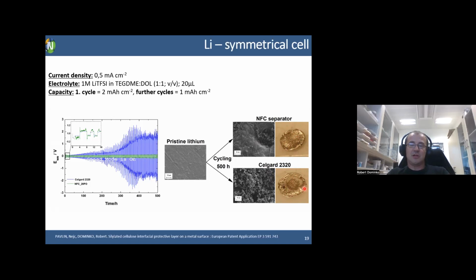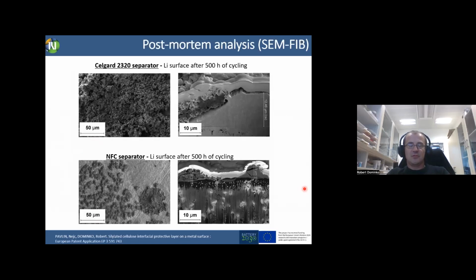For that reason we moved further. Also here, we saw that this degradation was stopped, it was not so heavily degraded, but anyway, we see this high surface area lithium formation on the surface of the lithium, and that means that sooner or later there will be intergrowth of the dendrites through the cellulose, which might create a short circuit with the cathode. And that brought us to the next step, and we started to think, okay, but how to deposit cellulose directly on the metallic lithium?